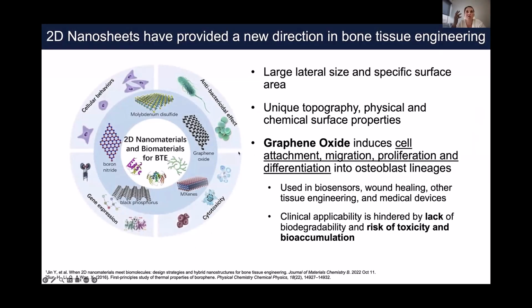There are even more papers on using graphene. Graphene is a 2D sheet of carbon. They measure a few nanometers thick and they have a very wide lateral dimension. They are usually exploited because they have exceptional electrical, chemical, and electronic properties. What has been shown is that graphene has a very high tensile strength when it's mixed with bioceramics. It promotes protein absorption, cell adhesion, and growth, and it helps the integrity of the ceramics. The problem is there are some concerns: there's no bioresorption, and they have some cytotoxicity